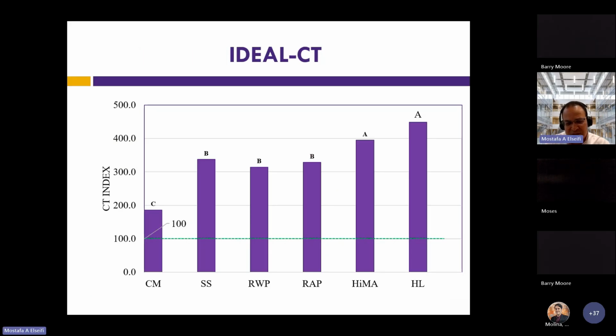In terms of the cracking resistance, you can see here, the higher the CT index, the better. And we had three groups. We had the hydrated lime and the HiMA as the best performance, which are shown on the right. Then we had the RAP, the recycled waste plastic, and the steel slag as the second best performer group. And then the control mix was the lowest performing group. So again, that indicates that the control mix that we use in real life will not perform as well as the other types of additives that we considered in this study.